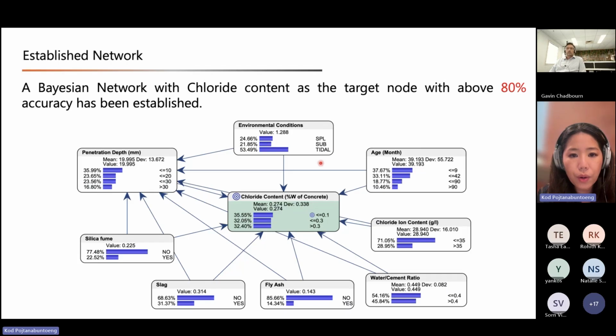And this one shows how the Bayesian network currently looks. This is the network that we developed, using the chloride content as the output. So what we want to know is the tendency for the chloride content at a specific condition to reach a certain value. In this case, we have less than 0.1, 0.3, or more than 0.3. So this is the outcome of the model.